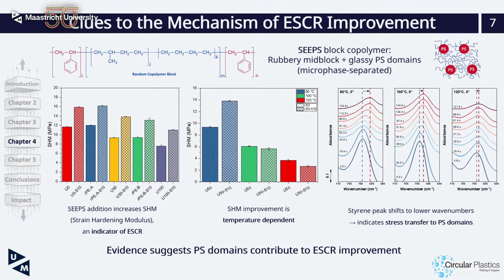Let's first look at the structure of this additive. This styrenic block copolymer is a SEEPS, styrene, ethylene, ethylene propylene, styrene block copolymer. These kinds of block copolymers often have a soft rubbery mid-block and rigid polystyrene nanodomains arranged in a microphase separated structure. To understand how this affects the slow crack growth and the mechanism behind ESCR, we looked at strain hardening